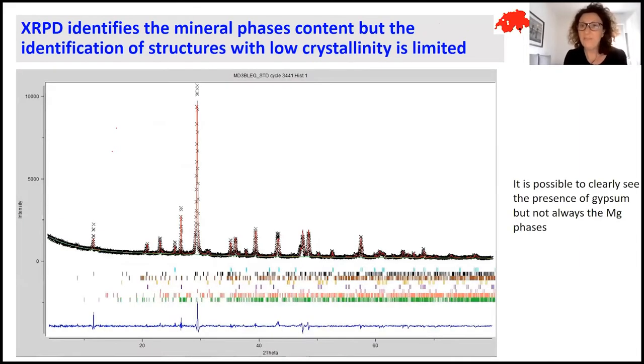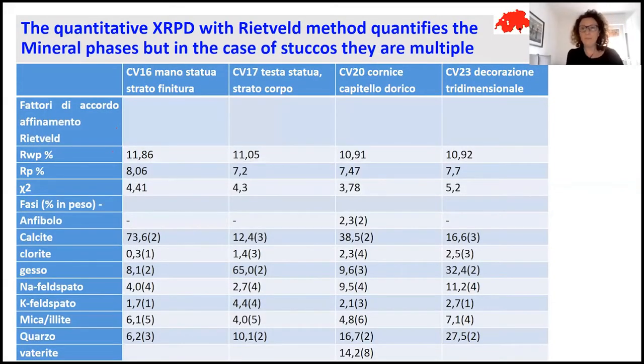Another possibility for the identification of the mineral components of a stucco and the quantification of the quantity of gypsum and lime is to use X-ray powder diffraction, which can give information about the mineral phase content. For example, also using the quantitative refinement with the Rietveld method, it is possible to have a quantification of the gypsum quantity and the lime quantity.